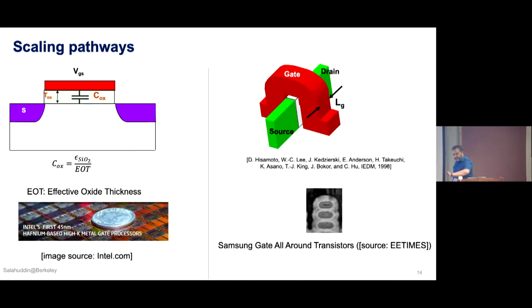Now, as I said, overall the industry has followed this scaling path. If you look at this as an insulator, the capacitance is given by the permittivity of SiO2 divided by the effective oxide thickness. Why we call this effective, I will talk about a little bit, but this is to some extent a normalized thickness of this oxide. So the first thing that happened is that we went to a higher permittivity oxide. That is what is called the high-K metal gate transition.